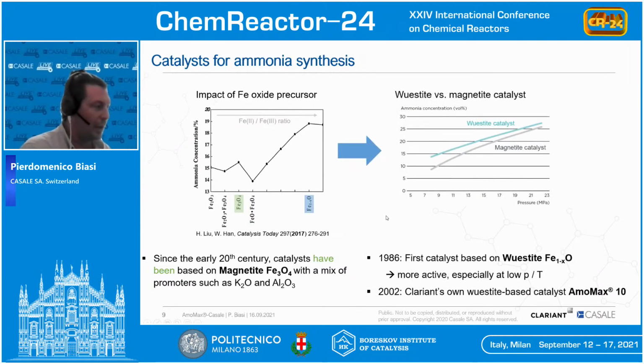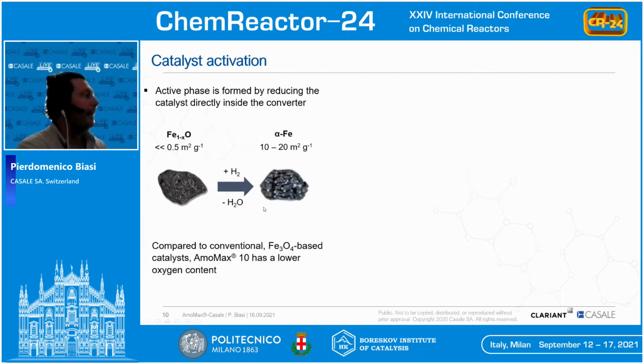And as you can see, Clariant acquired the wustite based catalyst, the Ammomax 10, in 2002. So as you can see on the right hand side, the wustite based catalyst is always better performing compared to the magnetite catalyst. This is because Clariant has also some proprietary precursors, some proprietary promoters that are added to the catalyst. So most important is also the catalyst activation, because a proper reduction of the catalyst makes the catalyst more or less active compared to what is expected. So it is important to know that